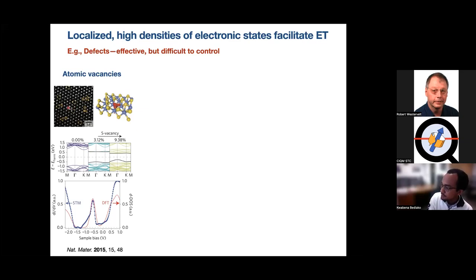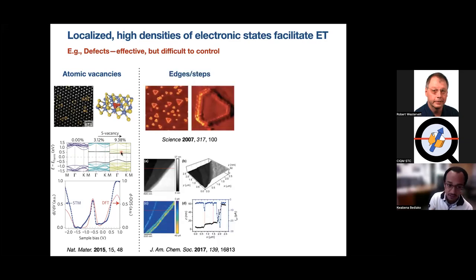And so, for instance, at molybdenum disulfide surfaces, sulfur vacancies have been shown to promote localized states that you can see in scanning tunneling spectroscopy data, and you can see from calculations how sulfur vacancies introduce more and more of these states in the middle of the band gap.